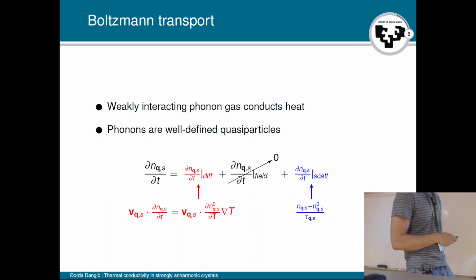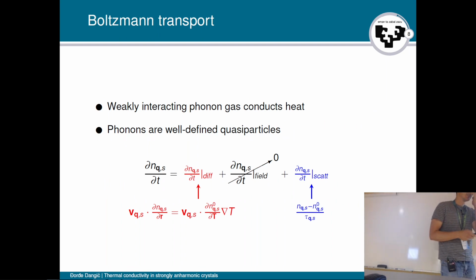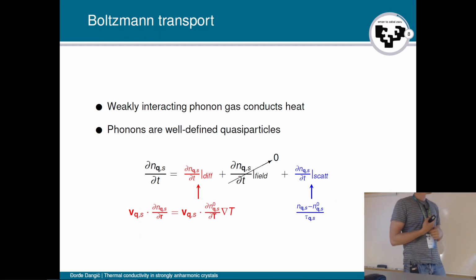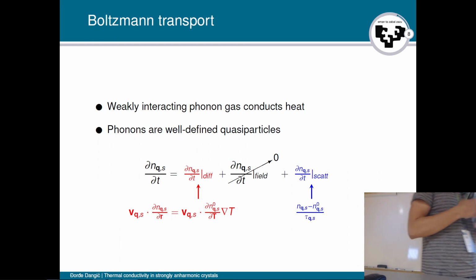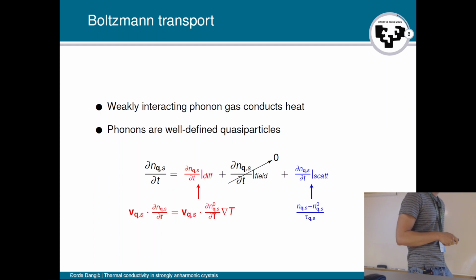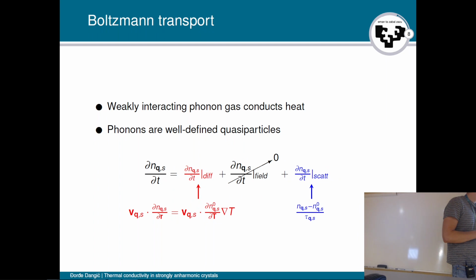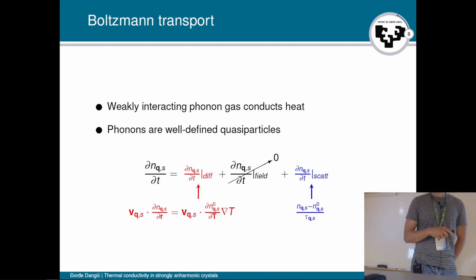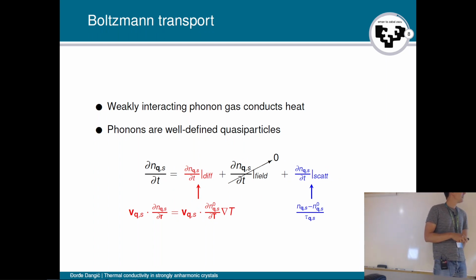So in the Boltzmann transport equation, we imagine that the heat is transferred by the weakly interacting phonon gas, which means that the phonons are well-defined particles. So basically, we imagine them as being gas particles that diffuse through the material. Then we take a look at the particular phonon state and the population of the phonon state, here denoted by n_qs, and we track its change in time. So why would this phonon population change in time? There are three main reasons.